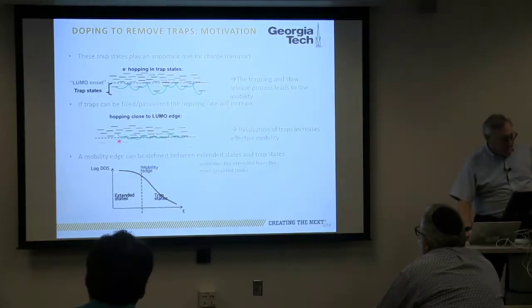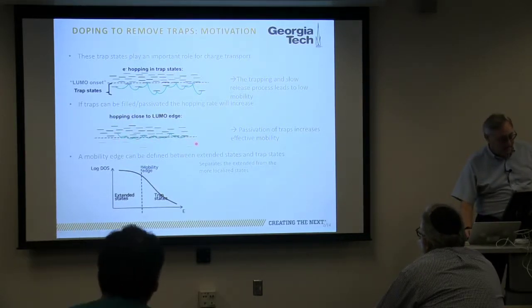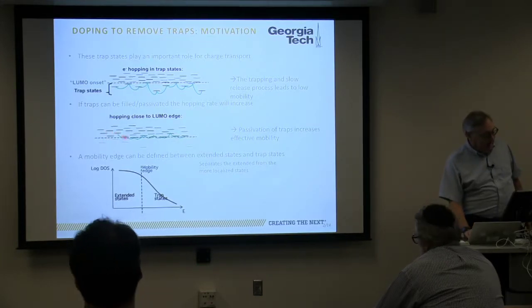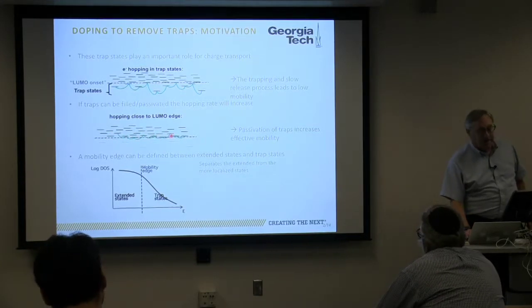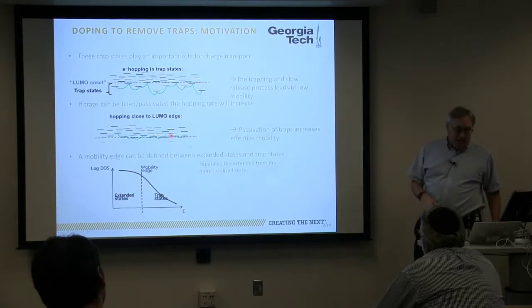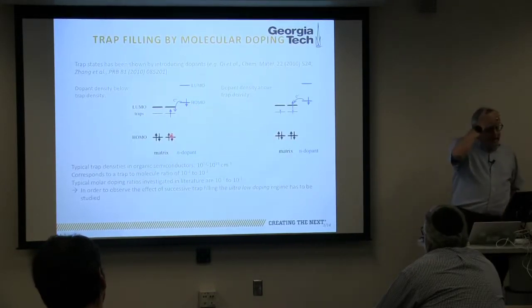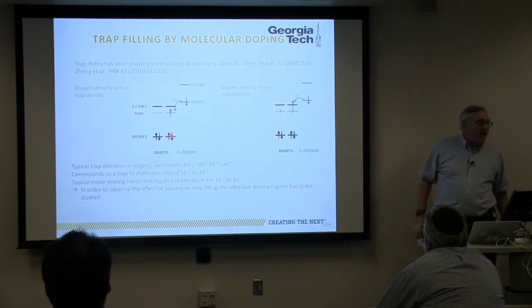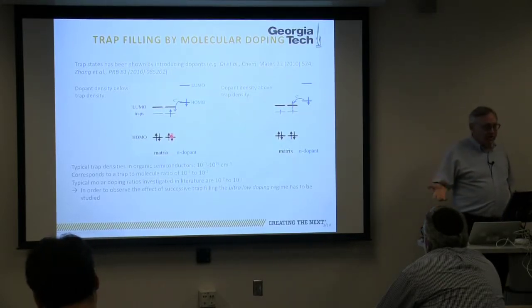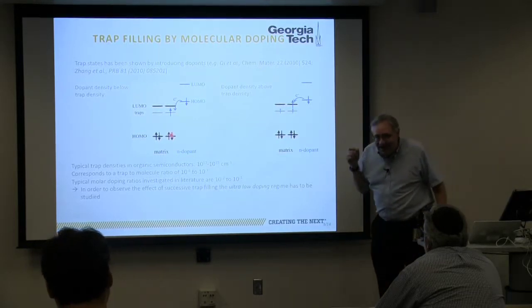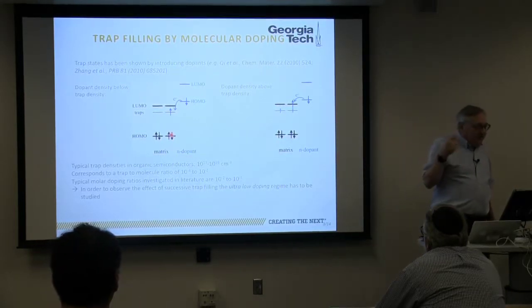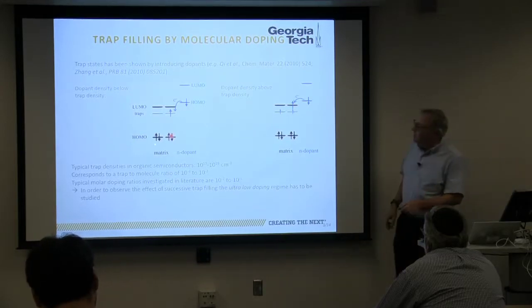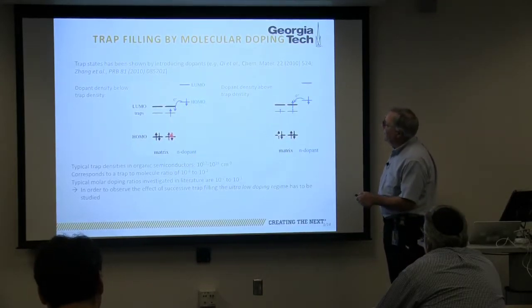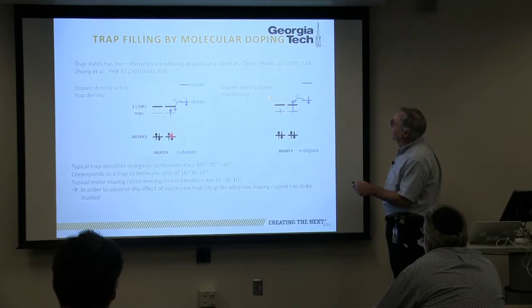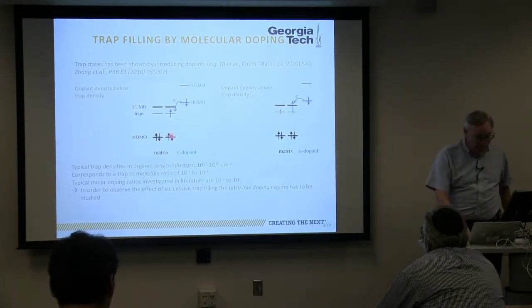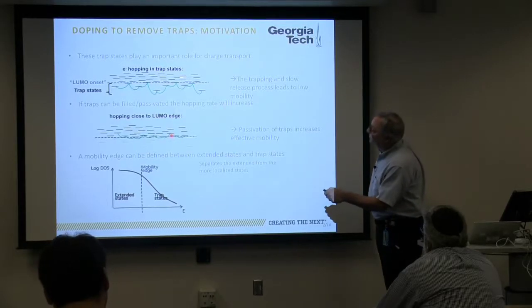But what if we could fill these low-lying states with electrons? Then we would only have to have the electron go from here to here to here to here, and the mobility would be higher. So you can do that, and the way we've done that is by having one of our dopants that's a strong reducing agent, and by just putting in tiny, tiny amounts of it, such that there's only enough of the dopant in the system to fill the trap states, but not enough to go and start filling this actual manifold of transport states.